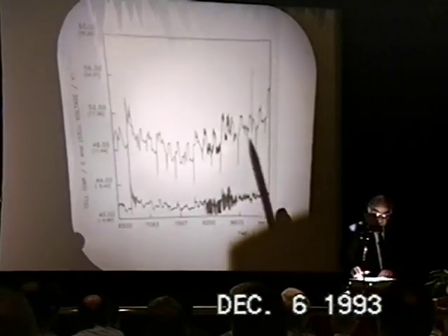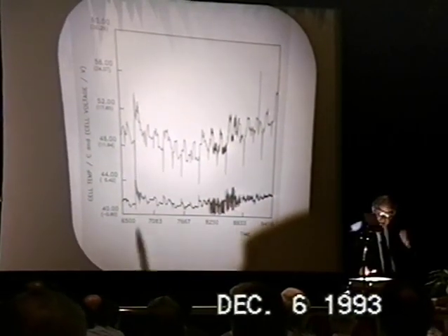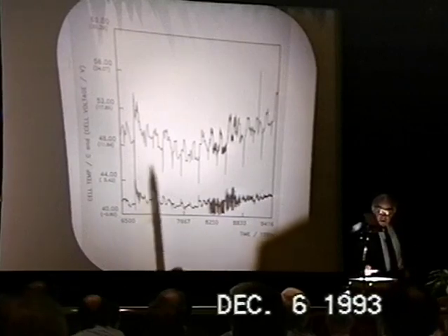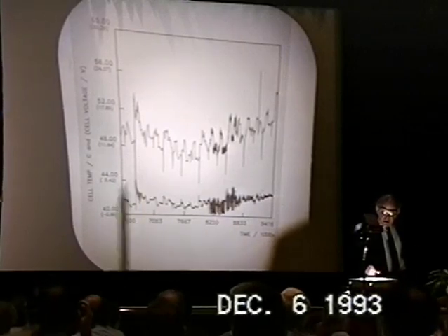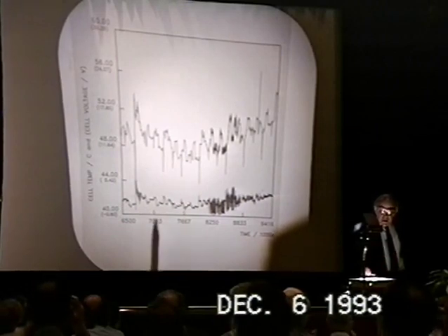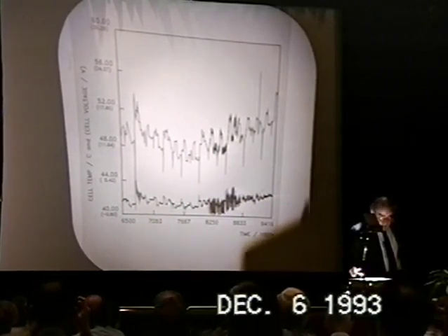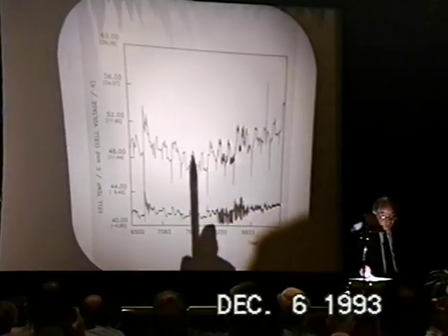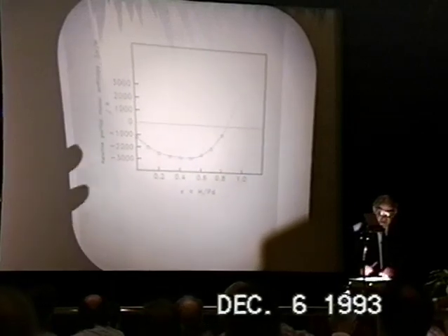And if you blow that up, you can see that to some extent there is a correlation between the cell temperature and the cell potential. So we are dealing with a strange attractor. We may be dealing with two strange attractors, and we of course have to find out the relationship between these strange attractors, or we may be dealing with a single strange attractor. So we know that we have to include the time dependence in this description. It's sensible to include the time dependence, and we can ask ourselves, why do we get these oscillations? And I shall use this overhead again later.